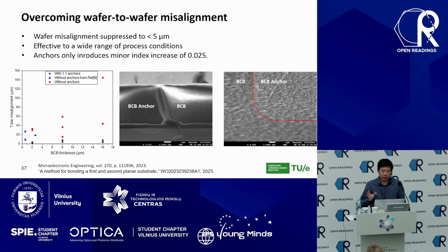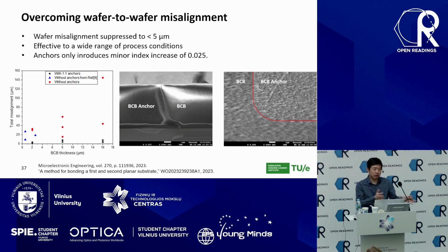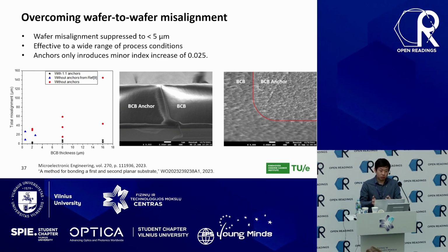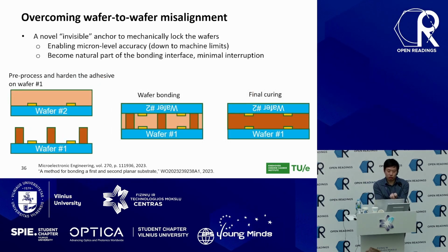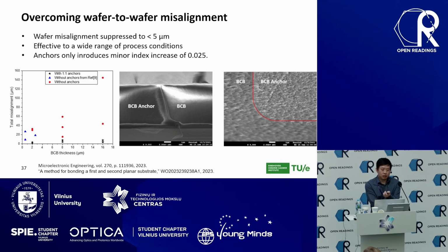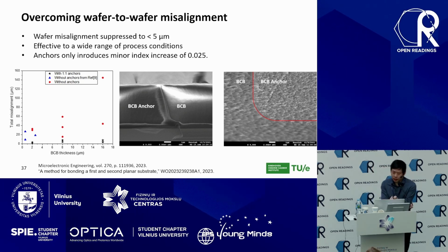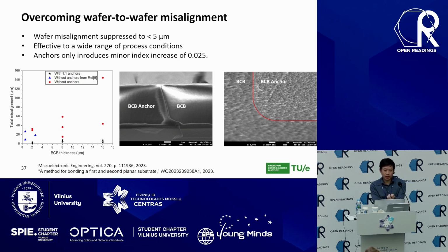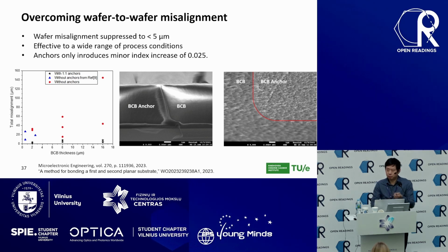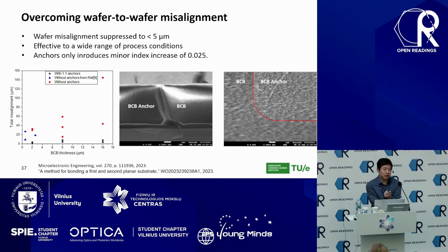Of course, people say, yeah, there must be some difference between your anchor and the rest of your bonding interface, because, like I've shown here, the anchor structure is actually cured twice. So we also tried to analyze whether there might be some mechanical strain induced or optical property change. You do see an interface here, right, between the BCB anchor we created and the regular BCB. And why is there an interface? It's because the anchors are cured twice, so it's actually denser. It has a higher density.